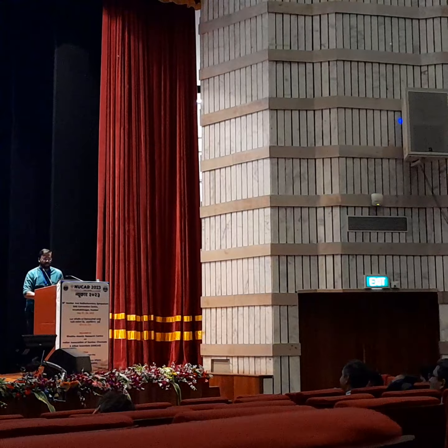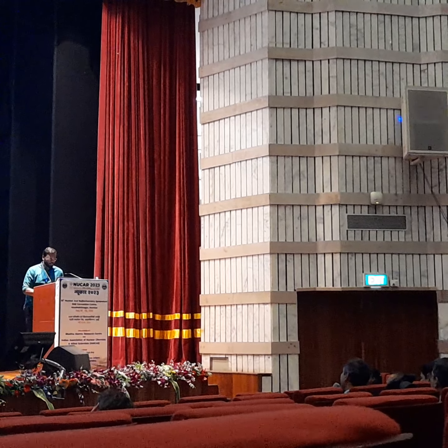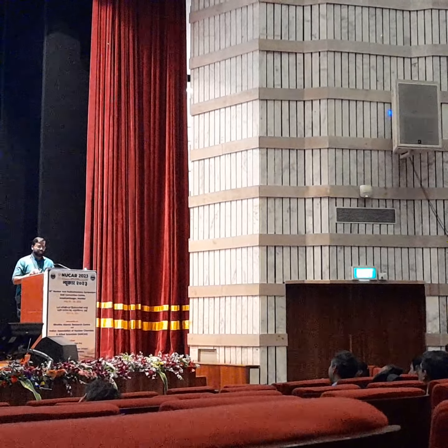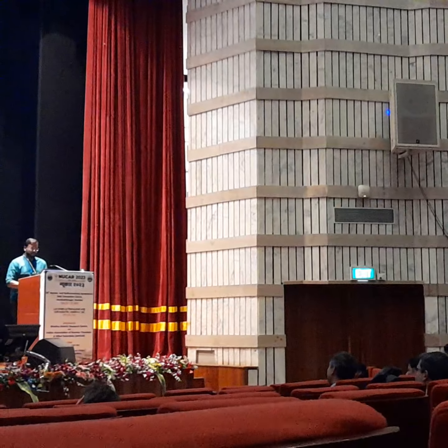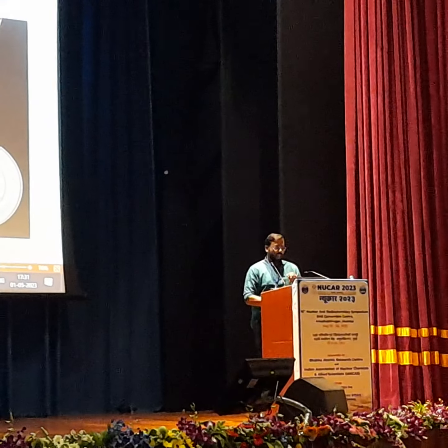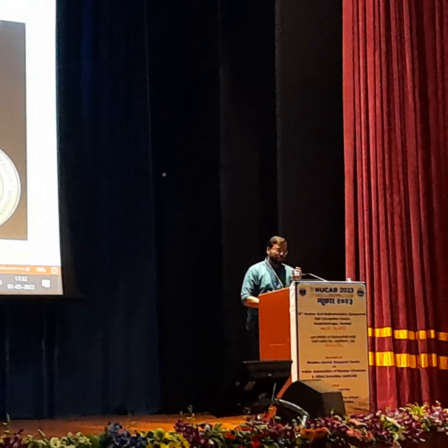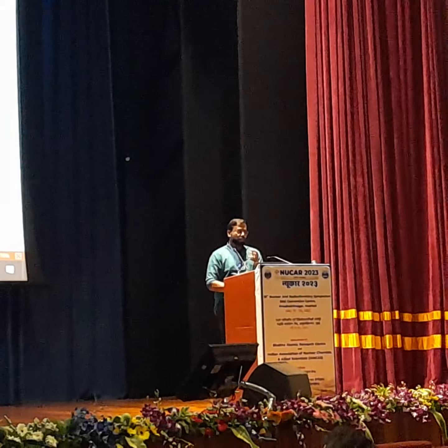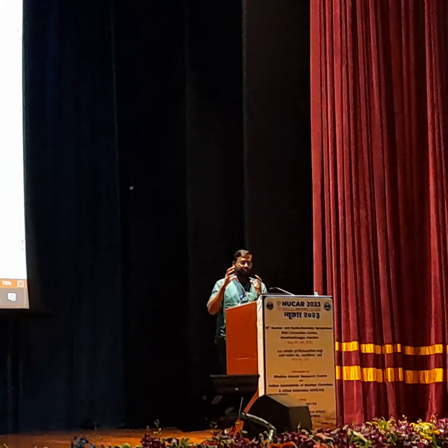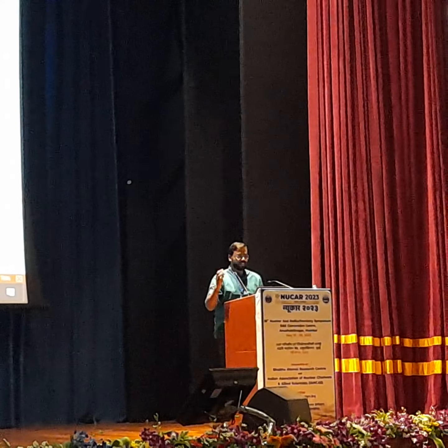Mr. Renjith, why did you select zinc for replacing cobalt? First of all, actually, sir, it is the vice versa. ZIF-8 is the most studied material, which we obtain by the reaction of zinc and 2-methylimidazole. Here I am trying to replace some of the zinc with cobalt, because the cobalt and linker bonding is stronger, so the flexibility will get reduced. That's the motive why I chose cobalt to replace some of the zinc.